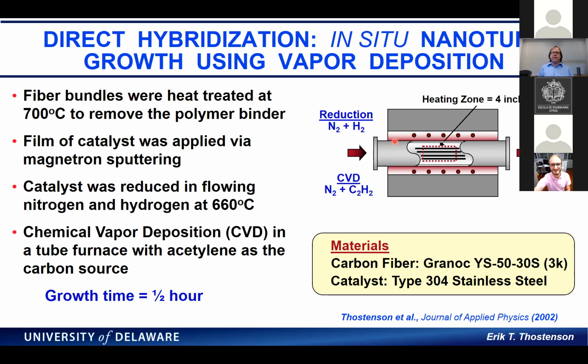This is a high temperature process, so it can be damaging to the carbon fibers, but it is also not applicable to a lot of other types of fibers such as aramid or glass fibers, which may soften, or certainly you're going to burn off the sizing, which is a chemical coating on the surface of the fiber.